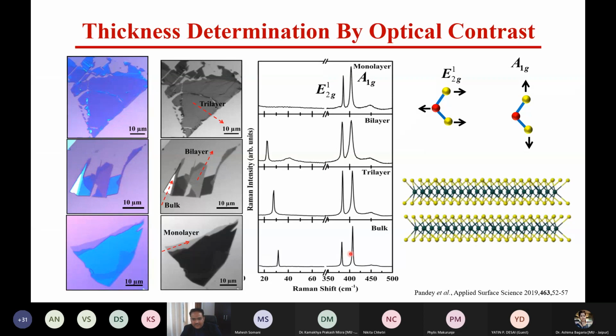in the Raman spectra. So these peaks, you look at here, this is for the monolayer, they are very close to each other, while for the bulk, they are far apart. Okay, so the gap between these two peaks will give rise to the identification of the layers, and these two peaks in the Raman spectra are related to these modes, which are like E_g modes related to the in-plane vibrations of the atoms, while the A_g is related to the out-of-plane vibration of the atoms here.